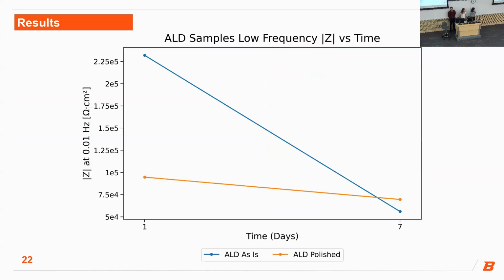We were only able to collect 2 EIS measurements for each of our ALD samples, meaning they were only in the sodium chloride solution for a total of 7 days. So these are preliminary results, but both of our samples started at about the same impedance as our welded samples and followed a decreasing trend, which was not apparent in our other sample sets. This indicates issues with the passive film forming, but again, we are looking at a much shorter time range than our other samples.